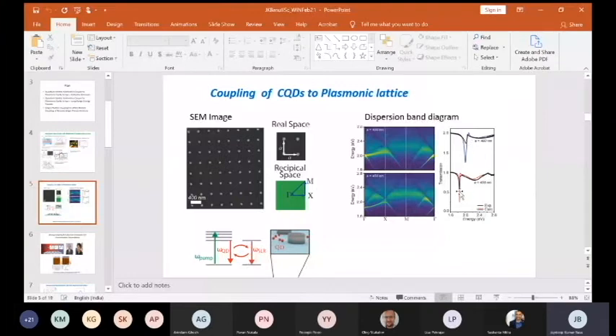But what you see here is this extremely sharp resonance, which essentially comes from this dispersion structure, and that is something which you can actually engineer by creating these arrays out of these metal nanostructures, which by themselves have this broad transmittance, but when combined in this lattice, they show this extremely sharp and narrow resonance lines and features, and you can tune the line width and the position by playing around with the parameters. The important thing is that these need to be diffractively coupled. That coupling is something which basically allows you to see the appearance of this mode.